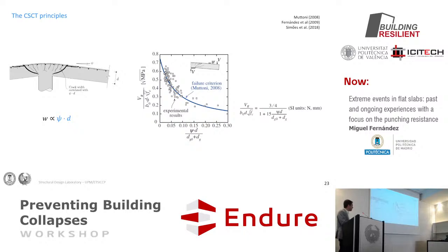And this is this assumption. So we assume that the opening of the crack width, W, is proportional to psi times d. And then when you compare what results from literature against this assumption, you see that they closely follow this region band, and then you can describe on average, with some uncertainty of course, with a simple failure criterion.